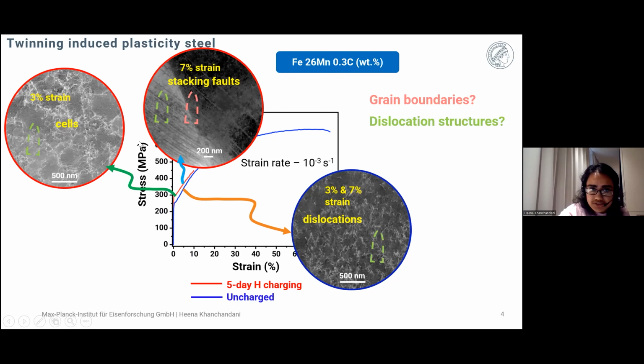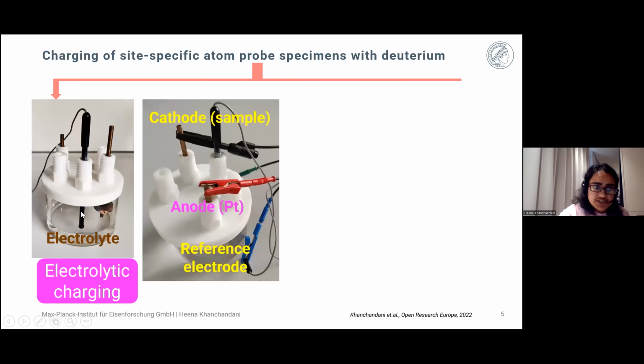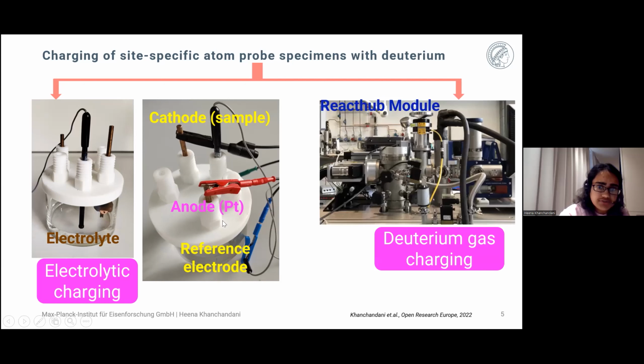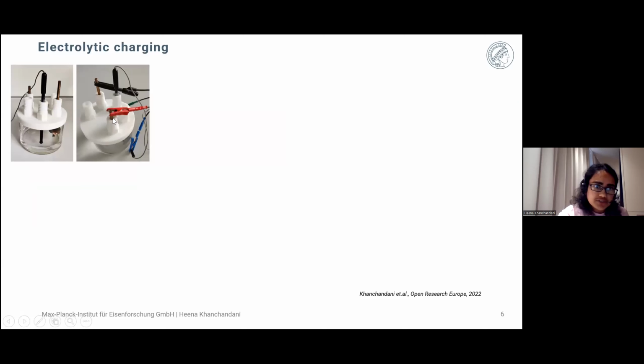To answer these questions, we had to find ways of analyzing these site-specific microstructural features with hydrogen by atom probe tomography. For this, we explored several methods. One of them was electrolytic charging for charging the atom probe specimens with hydrogen, which is conducted in this electrolytic cell. Here the electrolyte is used as a charging solution, and the sample mounted on this cryogenic puck is connected to the cathode, while platinum wire is used as anode, and there's a reference electrode. Alternatively, we also developed a gas charging method in a gas charging chamber, which we called the Reacthub Module. Firstly, I'll talk about the electrolytic charging method, which was conducted in this setup.